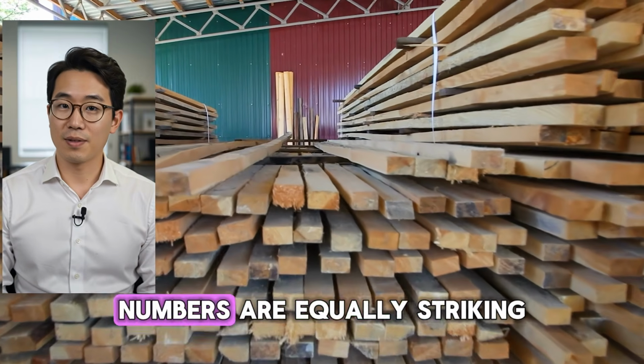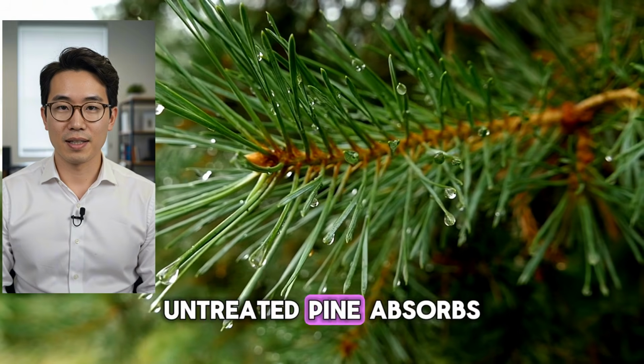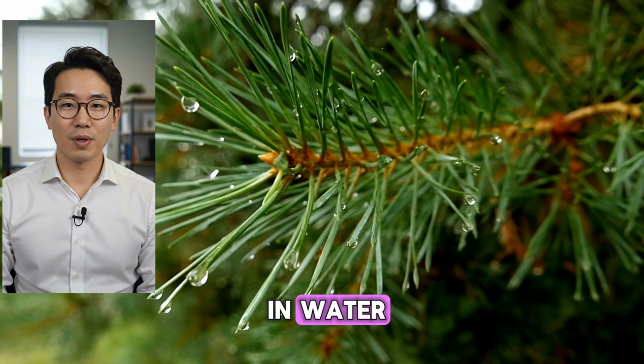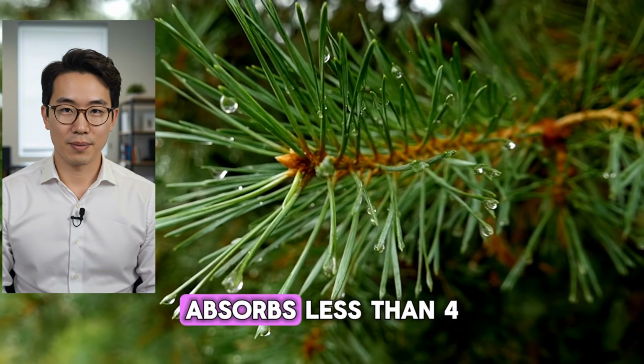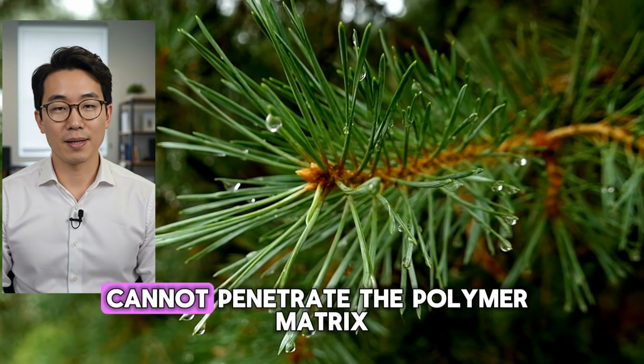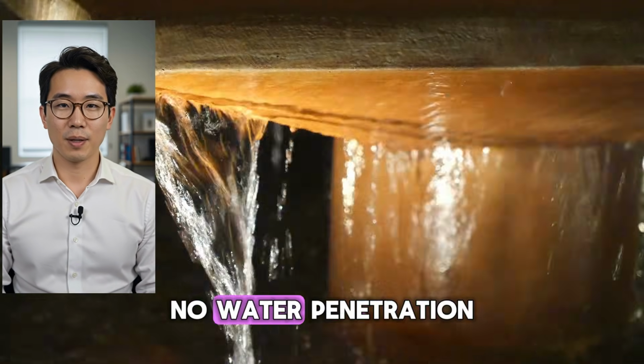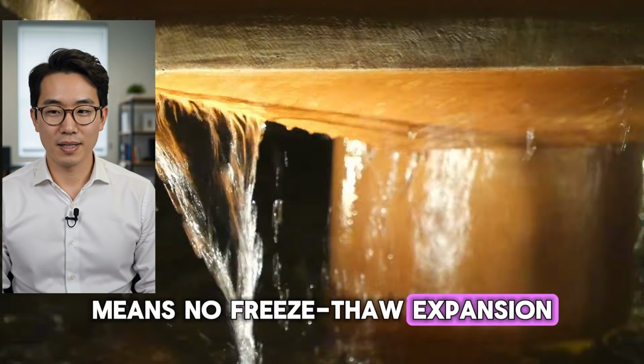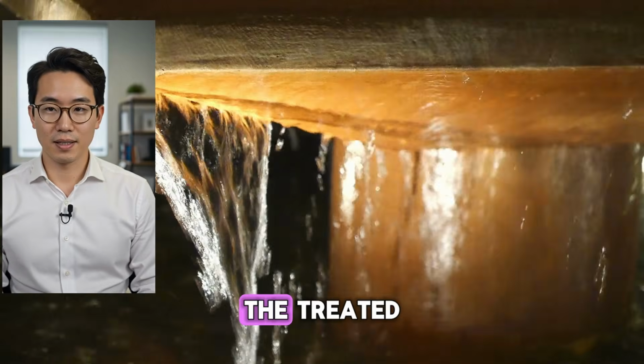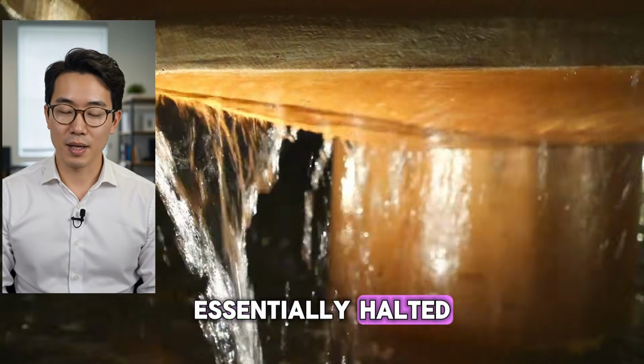The moisture resistance numbers are equally striking. Untreated pine absorbs 35% of its weight in water. Fully resin-treated pine absorbs less than 4%. Water cannot penetrate the polymer matrix. No water penetration means no freeze-thaw expansion, no mold, no rot. The treated wood's decay process is essentially halted.